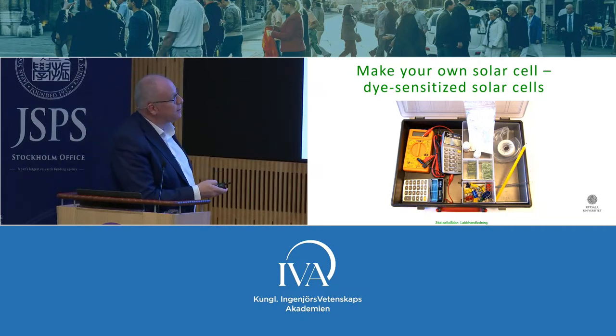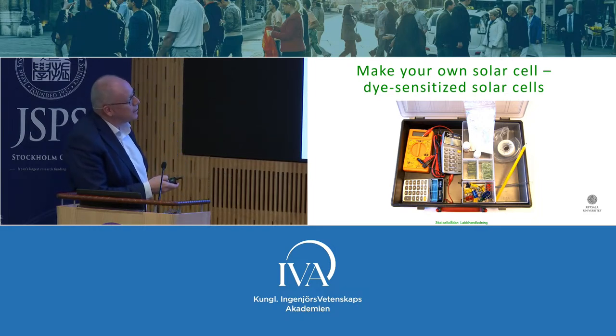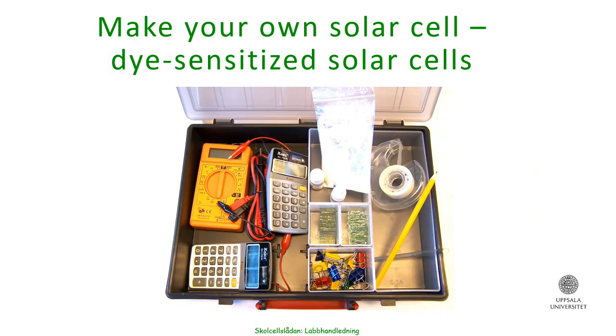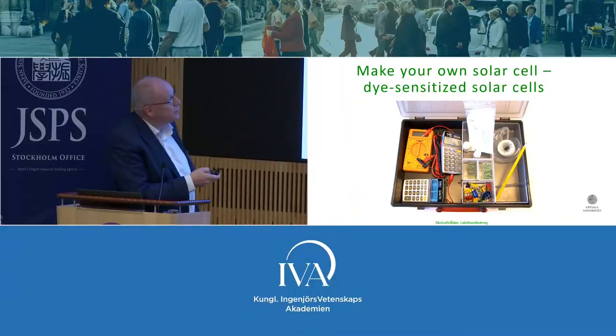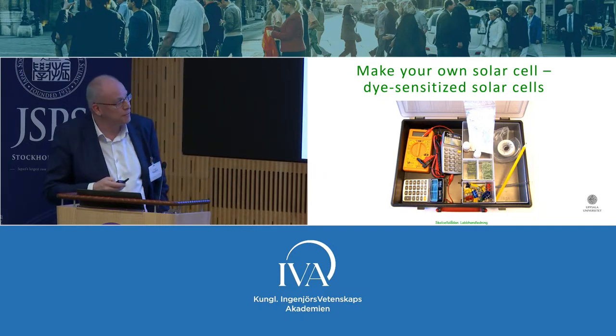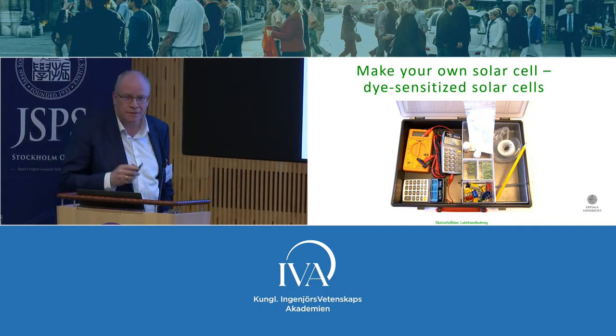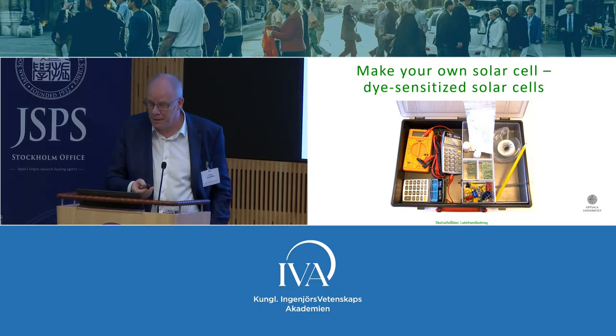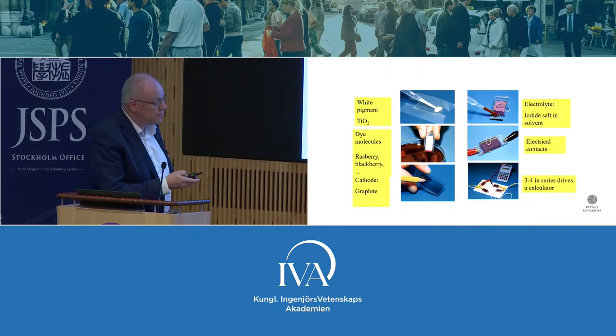So this was a solar cell kit we developed some years back, where you have the ingredients. This is our contact. It needs to be a transparent contact, a glass with a conducting layer. We have the titanium dioxide, white powder. We have the electrolyte with an iodide salt. And then we have a scotch tape to prepare them and some contacts. You have a pencil. The lab, which was developed for high school students, should then build their own solar cell and drive the calculator as their sort of delivery, if we say so. There is one ingredient missing, and that's the dye itself. And that's where the fun part of the lab starts. So here is how you can do it then.